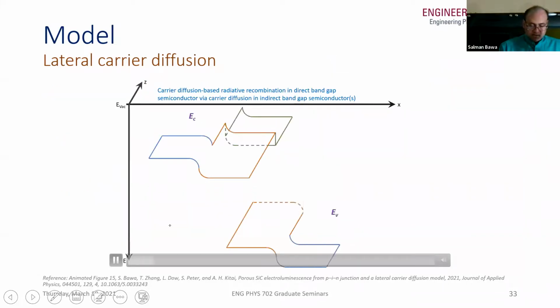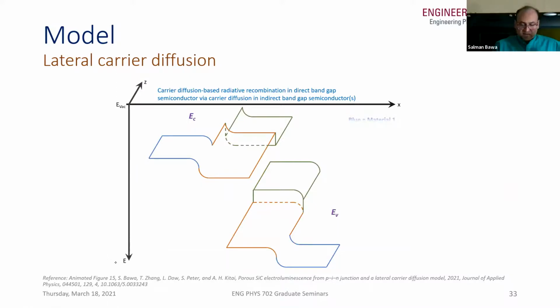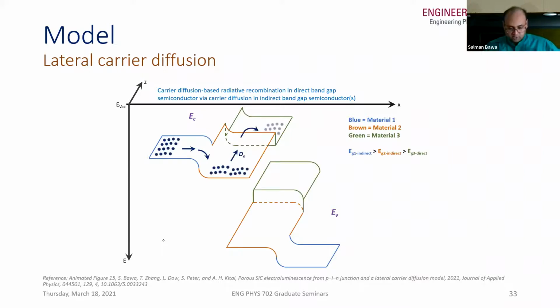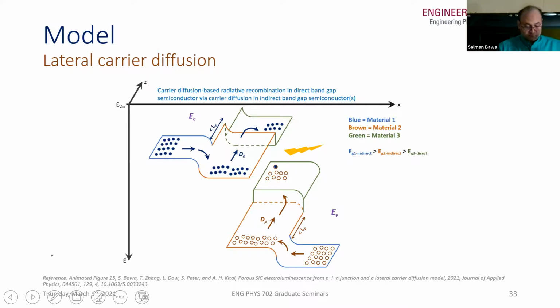So here we want to show you an animation, and what you see is a spatial band diagram where you see 3 different materials: the material which is blue, the material that is brown, and the material that is green. The blue is EG1, the brown is EG2, and the green is EG3. Blue and brown materials are indirect, and the green is direct. So what you're going to see is that the electrons are essentially going to drop into the material of EG2, the brown material, where they will then diffuse and drop into the material of EG3. The holes will follow the same trend, but actually bubble up. And once they are in the direct band gap, that is where they will then radiatively recombine. And remember that we need to take care that the width of the EG2 device is less than the carrier diffusion length for diffusion to occur.